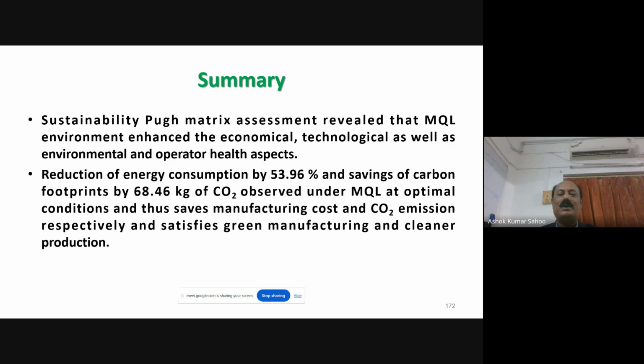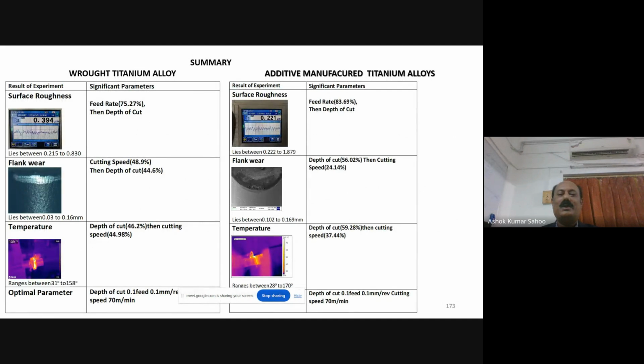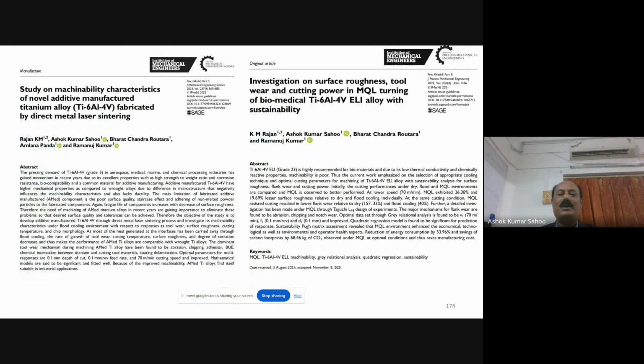Reduction of energy consumption by 53.96% and savings of carbon footprint by 68.46 kg of carbon dioxide emission were observed under MQL at optimal condition, thus saving manufacturing cost and carbon dioxide emission, and satisfying green manufacturing and cleaner machining operation. These are some of the comparative results between the raw titanium alloy and additive manufactured titanium alloy, where the work has been published in various journals, IMechE Part C and Part E, on the machining of novel additive manufactured titanium alloy developed through the direct metal laser sintering process. The same findings are reflected in these two journal articles.